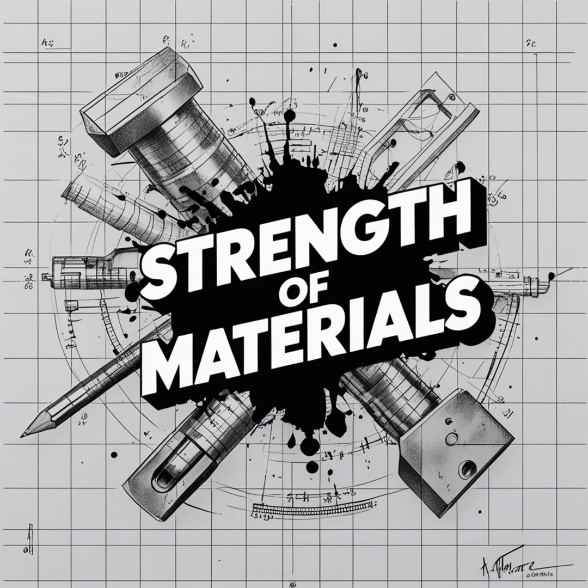Okay, so on one side of the ledger, you have your stress amplitude, how hard you are bending or pulling the metal. Right. And on the other side, you have the material's innate fatigue strength coefficient, which is basically its true strength in a single massive pull, scaled by the number of times you're cycling it, which is the Nf part. And the crucial part is that the number of cycles is tied to an exponent, right? That b you mentioned, the Basquin exponent.